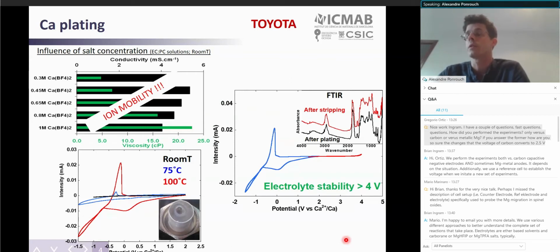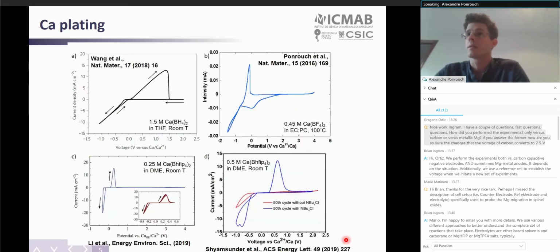With these first generation electrolytes, even working at such high temperature as 100 degrees C, we were able to have an electrochemical stability window over 4 volts. Since then, several groups already started to work on this field, and several plating and stripping reports appeared at room temperature as well.